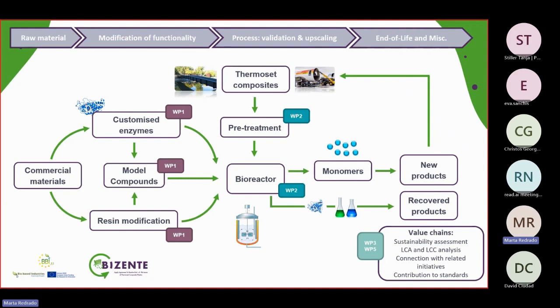Once we had them both at lab scale, we used model compounds to simulate this and also to find out what the products of this reaction would be. Once we had those first stages, we moved into the bioreactor, and for that we used thermoset composites that the industrial partners gave us from both the construction and the aeronautical sectors, and we pre-treated them in two ways, chemical and mechanical, and then we put them in the bioreactor and studied the whole process. From there, we got some products that were recovered, and on the other hand, we wanted some monomers that could be reused, and we studied what other life we could give to these monomers to introduce them back in the market.